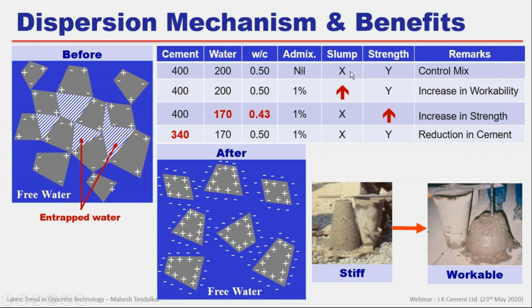If there is no admixture, we get X slump and Y strength. So this is a control mix. The moment we add, say, a 1% dose of admixture, because of the admixture this water is freed. So what will happen? Slump will increase, so there is an increase in workability. But our target is not to increase the workability. We are happy with the same workability.